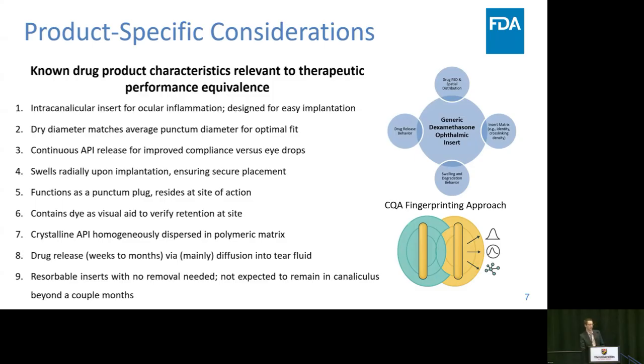So for a generic dexamethasone ophthalmic insert, there's basically some key properties that would have to be considered when evaluating sameness. The drug particle size distribution and spatial distribution within the insert itself is important. The insert matrix, so in terms of the identity, the Q1, Q2 aspect of that, as well as the cross-linking density that ends up happening after the curing, the swelling and the degradation behavior that the insert features, as well as the drug release behavior. And so ultimately, all of this leads to an approach that's kind of like fingerprinting and requires a totality of evidence type of approach, where you look at all these different orthogonal aspects of the product to gain a comprehensive understanding when it can be difficult to measure these in other direct ways.